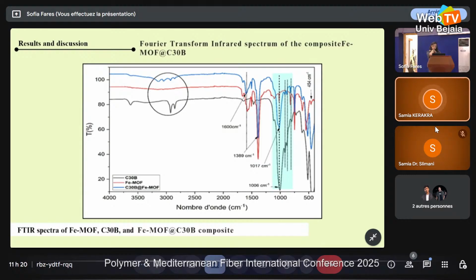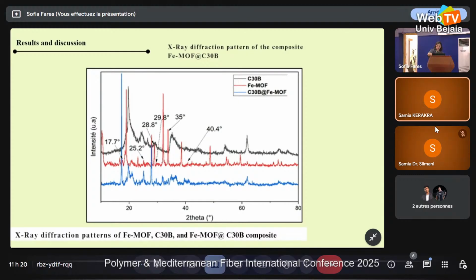These results confirm the successful synthesis of our composites because both clay and the MOF preserve their structure. In the X-ray diffraction pattern of the composite, as can be shown in this figure, the MOF exhibits distinct peaks, confirming its crystalline structure. And in the composite, the pattern shows the characteristic peaks of MOF and a broad peak from clay, indicating successful incorporation of the clay in our MOFs.